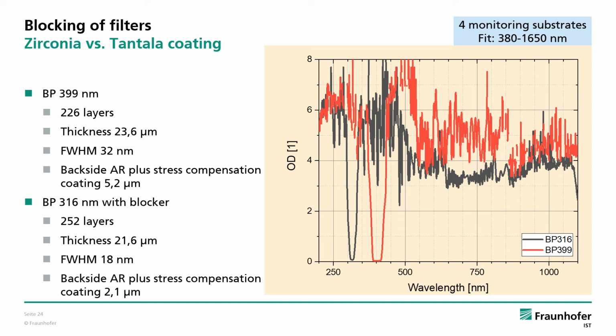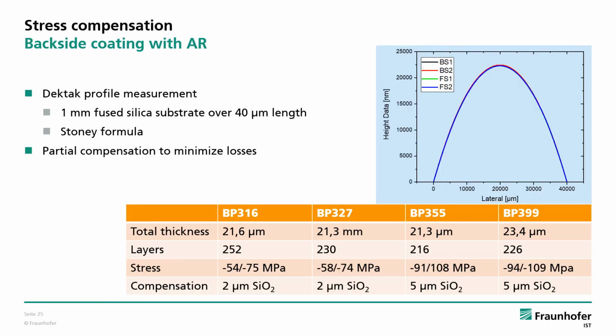Because of the slightly lower refractive index contrast and smaller full width half maximum, the bandpass at 316 nanometer needed some more layers than that at 399 nanometer, although the density is lower in the visible range. We needed some stress compensation to meet the surface figure requirements. This was done as a silicon oxide layer below the anti-reflective coating on the backside.